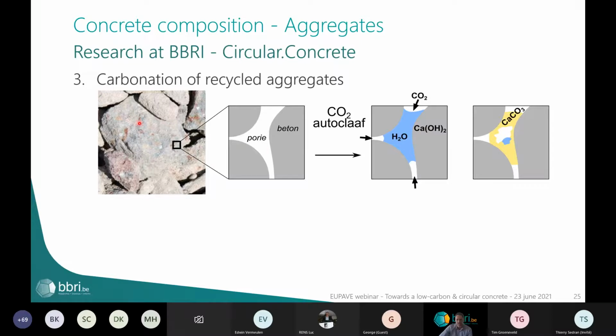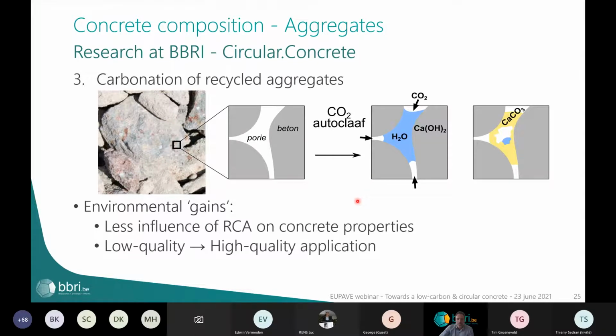The recycled aggregates contain a large portion of mortar, and this mortar can be carbonated just like ordinary concrete. In ordinary concrete, it's not good that it carbonates because it's not good for the rebar inside the concrete. But in fact, the concrete itself gains in strength and becomes less porous. And this is what we want to do with the active carbonation of recycled aggregates, so that the mortar portion attached to the original natural aggregates becomes less porous. And you can see here, calcium carbonates will fill up the voids inside the concrete, so that it becomes less porous and stronger and less susceptible to ingress of CO2 and water.